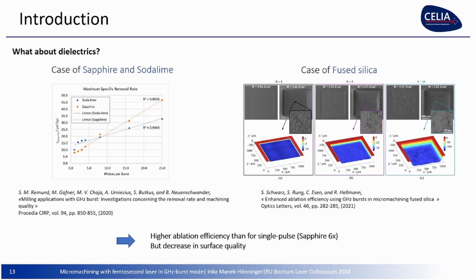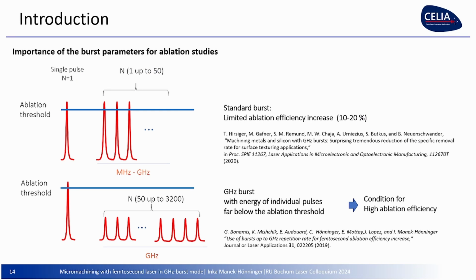But sometimes also the opposite was observed. Sometimes people observed, for example, Beat Neuenschwander on metals, not an increase, but a decrease of the efficiency. So how does this go together? He used a standard burst. The answer is in the laser parameters. What are the burst parameters? Here in this paper, Beat Neuenschwander showed a surprising, tremendous reduction of the specific removal rate.